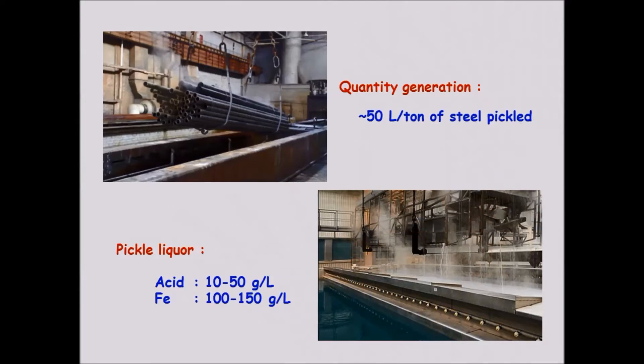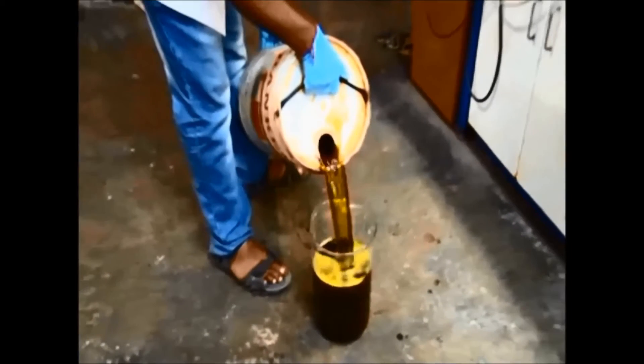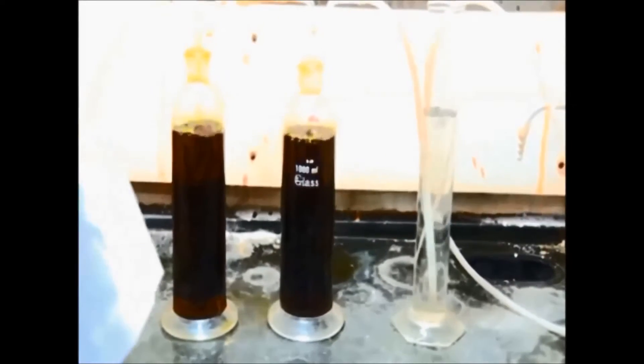The chloride steel pickling process produces about 30 to 50 litres per tonne of steel pickled, containing 100 to 150 grams per litre of ferrous iron. Ferrous chloride from various sources is converted to its ferric form.